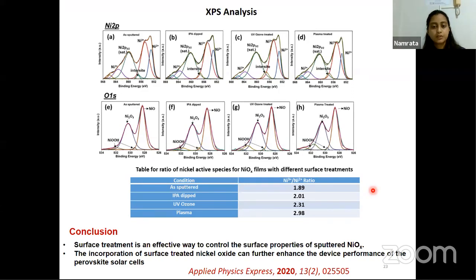So for that, we measured the X-ray photoelectron spectroscopy. And from here, it was quite clear what might be happening. Like in the previous results, we were getting a hint that the surface of nickel oxide is influencing. Here we see that with different treatments, we have a different ratio of nickel 3 plus to nickel 2 plus. We have a different ratio of these species on the surface of nickel oxide. And these species are governing what is happening during the interaction of the perovskite and the nickel oxide.